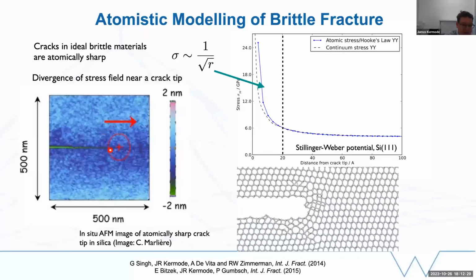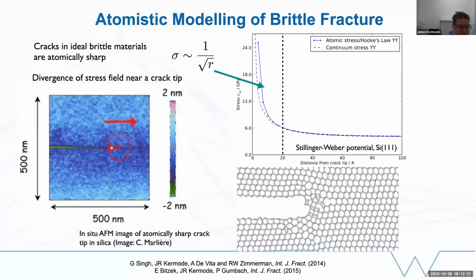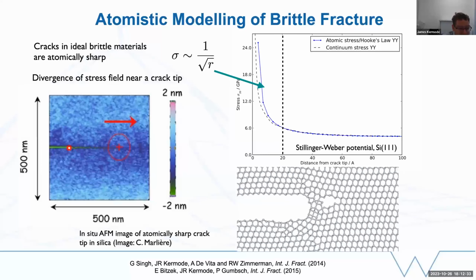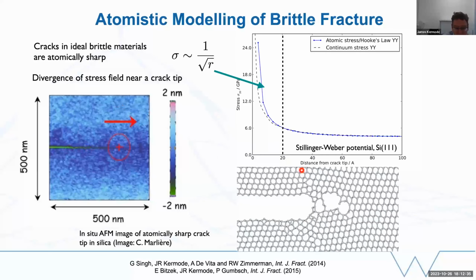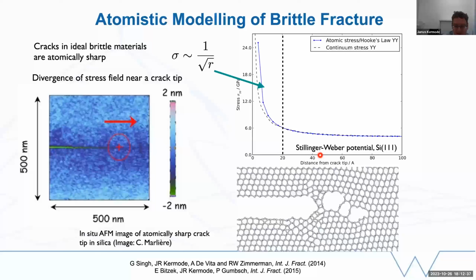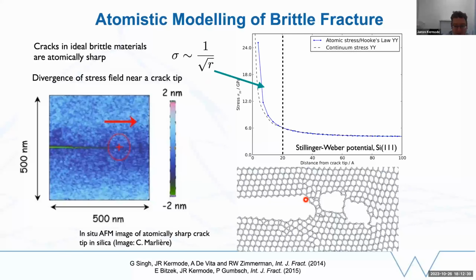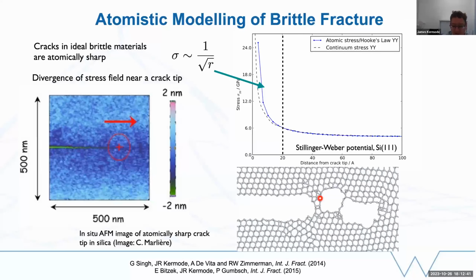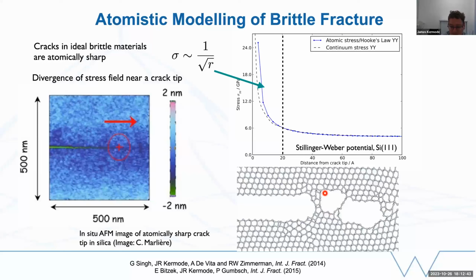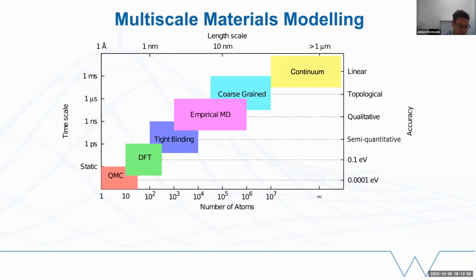So if we look in an experiment, we see an atomically sharp crack tip. This is an AFM. We see it's really very, very sharp, whereas in a simple simulation with a classical interatomic potential, we massively overestimate the amount of energy that we have to feed in order to initiate fracture, and we lead to all these messy processes here, which are not correct and are not seen in an experiment because we're not describing bond breaking correctly.